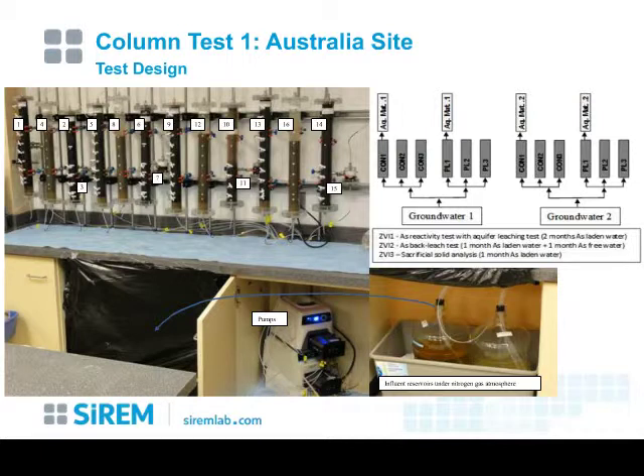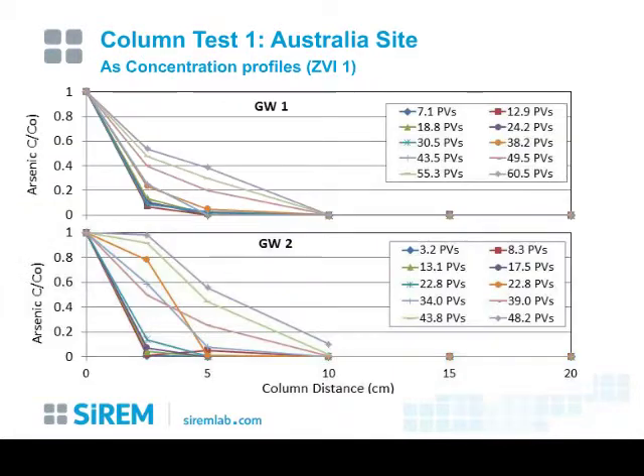Column 2 was zero-valent iron run for a month with arsenic impacted water, and then flushed for an additional month with arsenic-free water to determine if the arsenic would be back leached from the zero-valent iron. And column 3 was essentially a replicate of column 2, but used as a sacrificial sampling device so that we could sacrifice that sample for spectroscopy and some of the leaching experiments that needed to be done.